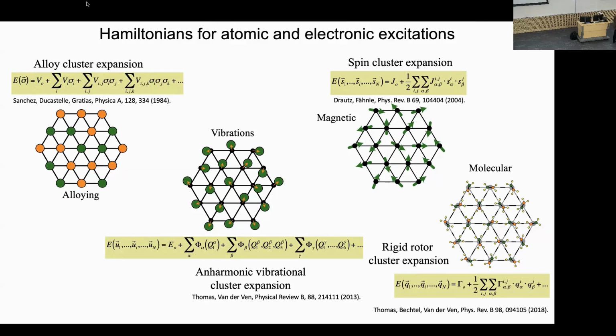You can also do it for vibrations. In that case, the degrees of freedom are not +1s and -1s, but actually displacement vectors, and these atoms are vibrating back and forth. And then you can come up with an energy expression that describes how the energy of the crystal depends on the current state of all these vibrating atoms. Or you could have a spin cluster expansion, so a generalized Heisenberg model, because a lot of these crystals are magnetic, so you've got magnetic moments. That's another degree of freedom. And the energy of the crystal will then depend on the relative orientations of these magnetic moments.